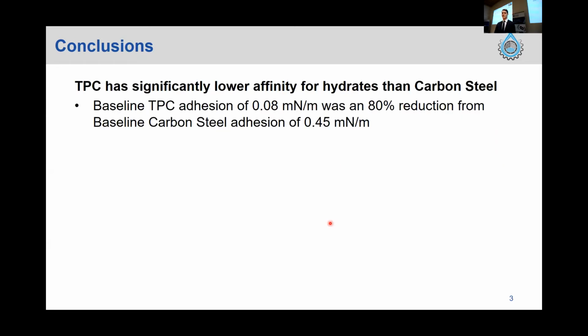I will begin with the conclusions of my work. The first, which was quite significant, was that the TPC material showed a significantly lower affinity for hydrates than carbon steel. This was confirmed in the testing, where the baseline adhesion for hydrates to this TPC material was recorded as 0.08 millinewtons per meter, an 80% reduction from the value recorded for carbon steel.